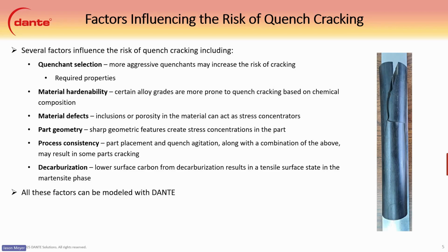And decarburization, like I said, we have an example on that later. The lower surface carbon from decarburization results in a higher tensile stress state in the martensite phase at the surface, and this is usually a major cause of cracking. And all these factors can be modeled with DANTE.